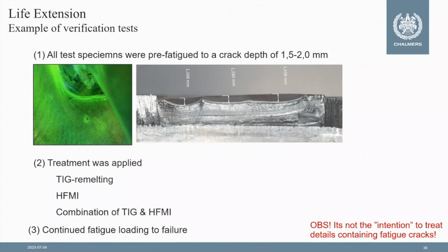As a disclaimer, it is not the intention that HFMI would be applied on a detail in which we detect, during inspection of a bridge, that cracks already exist. In the research work itself, in order to make sure that we are testing the worst scenario, we have been testing these different specimens until cracks of 1.5 to 2 millimeters deep are detected. Then we stop the fatigue testing, do the treatment, either directly HFMI or TIG remelting or a combination of these two, and then we continue fatigue loading and see what kind of extension we get in fatigue life. That's in principle the method of verification.